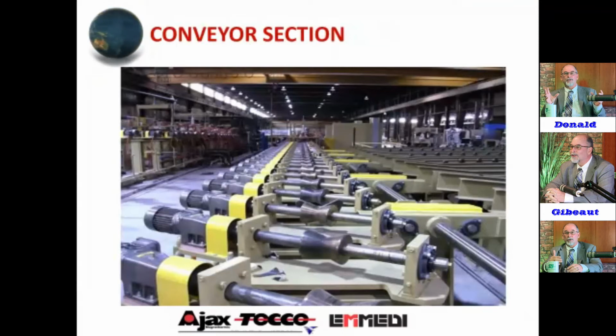But again, on these lines, when you have pipe coming in and going through the austenitizer, not all that pipe is perfectly straight. And when it goes to the austenitizer, it sometimes gets squirrely with the stress relieving. So you're hitting on these rolls quite often. The cantilever design does work. We can offer it, but all of our lines out there have this bearing at the end to fully support that roll. And we believe it truly helps the alignment of this line, which is critical to the straightness on these lines.